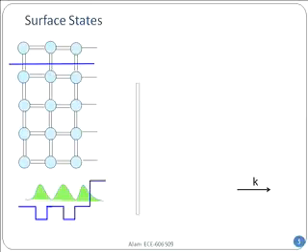Trap levels were foreign atoms like gold or copper coming into silicon. So this was physically a different material that gave a different trap level. Here, there is no foreign material. It is just that I have terminated the barrier and therefore I have introduced a level which is a solution of the original Schrodinger equation, but with a new boundary condition, you see.